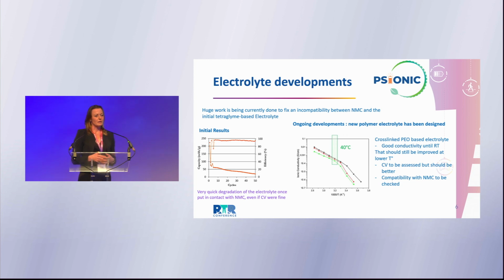What was interesting in this project was that we discovered that even with cyclic voltammetric measurements that were good at high potential, still 4.5 volt, when you put the right electrode, it's a completely different world. So our electrolyte was stable in theory at 4.5 volt. But when we put it against NMC, it was not functional. So we are currently redeveloping the electrolyte, improving it to make it compatible with NMC and allow it to work in the real system.